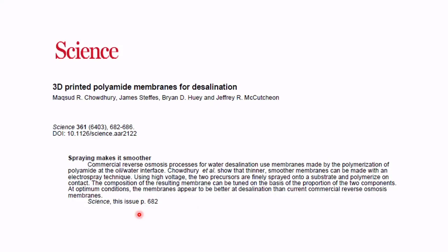And another really neat thing I would like to mention is this other paper. Again, not necessarily related to my research anymore with the membrane leachates, but a really neat avenue to producing membranes is 3D printing polyamide membranes for desalination. So this paper actually found that reverse osmosis membranes, instead of producing them the way that they're produced now with the polymerization reaction, they can actually use 3D printers to produce these membranes, and at optimum conditions, the membranes appear to be better at desalination than commercial reverse osmosis membranes. So I thought that was kind of neat in terms of innovation and using new technologies to improve a treatment technology.